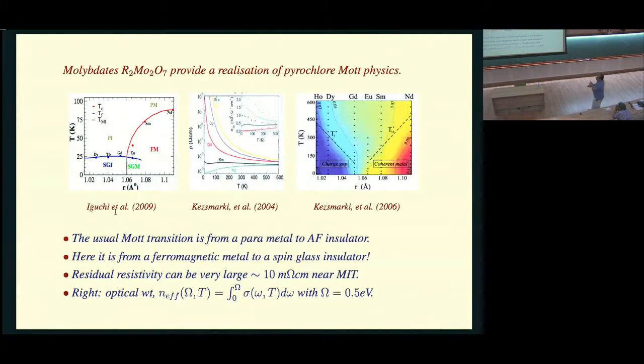The ferro is unusual in Mott insulators, but has a simple understanding when we go to the next slide. However, if you go to large values of U by t, so this is insulator, this is metal. The metal, rather than being a parametal, is a ferrometal. The insulator, rather than being antiferromagnetic, which anyway is not allowed on this structure, is a spin glass insulator. And the typical scale for this is about 100 Kelvin, and about a 20 Kelvin scale for the spin glass insulator. If you look at the transport in the insulator, so these objects, Dy, Tb, Gd, blow up as T goes to 0, Nd seems to go to a small value, Sm goes to a value.